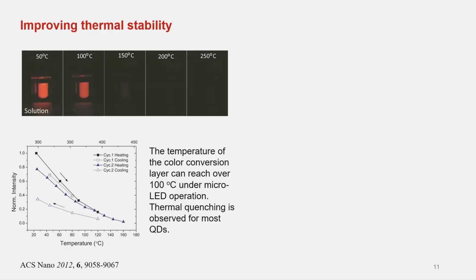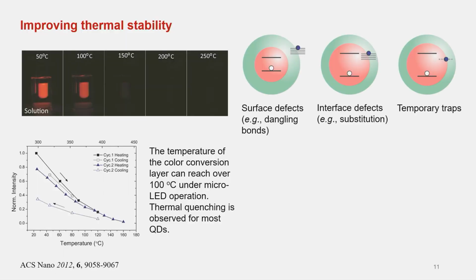The second part is thermal stability. In the quantum dot field, it's known that if you increase temperature, especially in air, it quenches emission. And people report that for the micro LED, you probably can reach over 100 degrees under operation. So there are tons of reasons or mechanisms people propose behind it. This is more on the cadmium side.